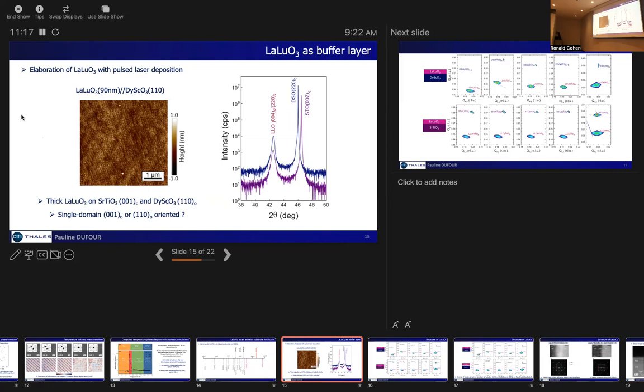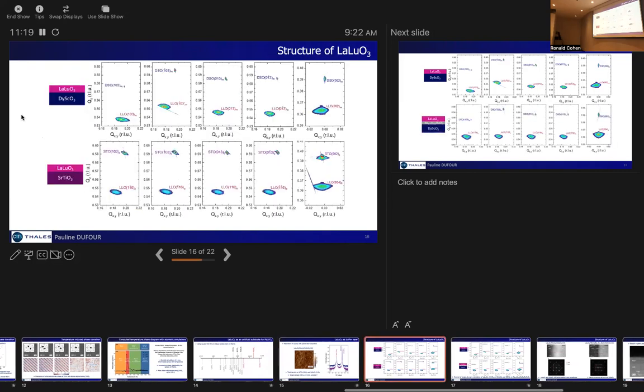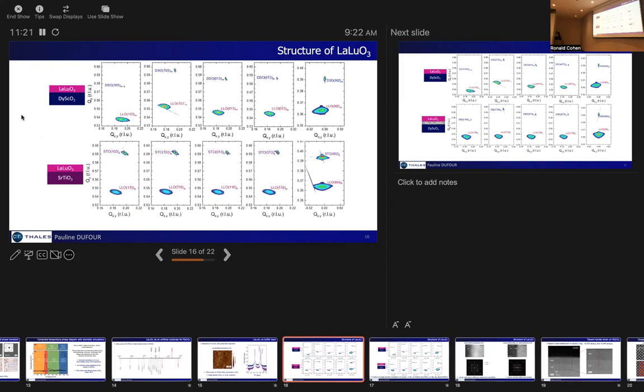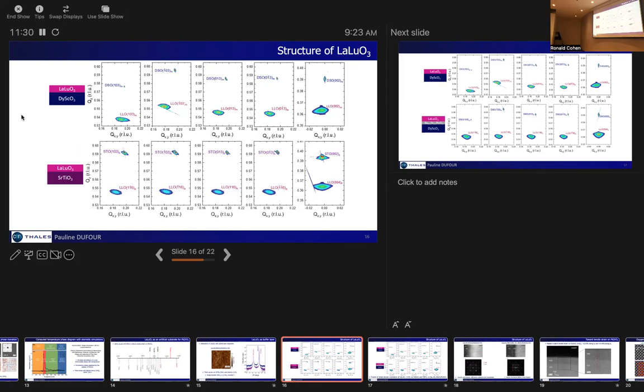And to discriminate between these different orientations, we performed reciprocal space maps on 2 films of LLO of the same thickness growing on DSO and STO. And interestingly, if you follow the spots of the LLO here and here, you will see that they evolve in mirror with those of the substrates. And indeed, we could see that when it's grown on DSO, LLO adopts the same orientation 110 as DSO, while when it's grown on STO, it adopts 001 orientation.